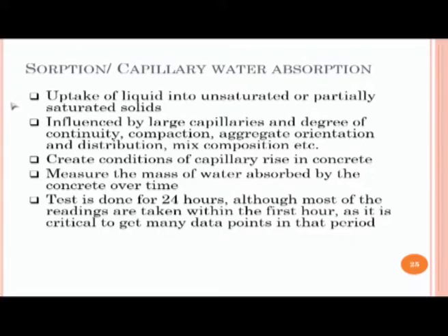So, basically sorption or capillary water absorption deals with uptake of liquid into unsaturated or partially saturated solids. This is influenced by presence of capillary pores and degree of continuity of the pores. Please remember, I talked earlier about the fact that it is not important that you have a lot of pores.